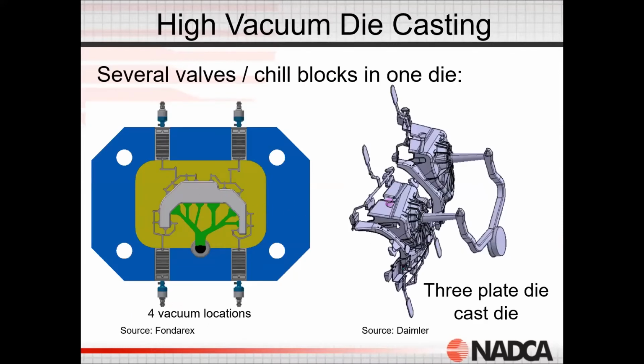So here's a 2-cavity, 3-plate tool, and it has a vacuum system. So we're injecting the metal in through the center of the casting. Here's another casting. This is the shot. This is the gating system. This is the actual part. And we have 4 vacuum valves coming through chill vents. So these are chill vents, and then each one of these is attached to an individual vacuum.